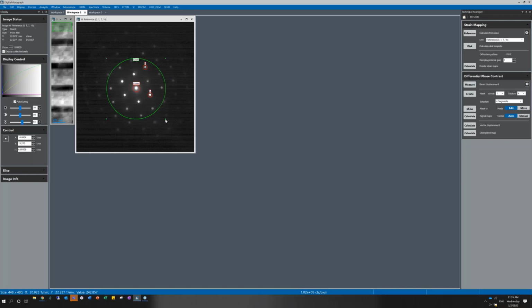And then this green circle tells the software how many orders of the diffraction reflections I want to include in my calculation. If you include more reflections that have high enough signal to noise ratio, you're going to improve the accuracy of your calculations. But if I make it this big and include those low signals, there is no point, because I'm introducing more error and also more computation time for my strain mapping. So I'm going to make it contain just these first order reflections for now. Now I'm ready to move to the next step.